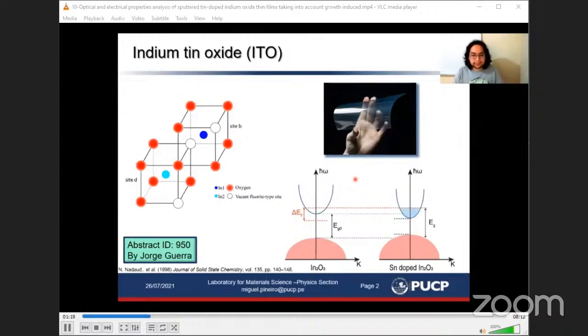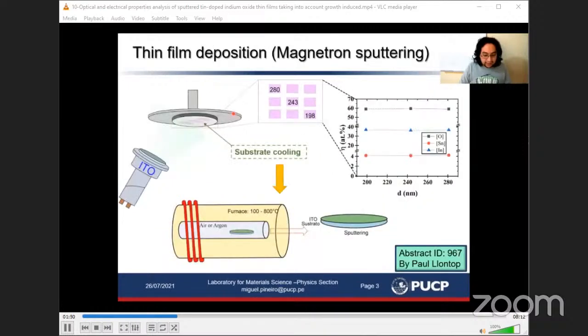Due to these properties, they are used in display devices, but these properties are affected by complicated microstructure created during the film deposition and post-deposition annealing. Because of this, we prepare ITO layers at low substrate temperature in order to induce inhomogeneous microstructure and tune the optical and electrical properties. So, how do we fabricate these materials? We prepare ITO thin films by radio frequency magnetron sputtering with substrate cooling active during the deposition process, without rotating, in order to have various samples with different thickness.